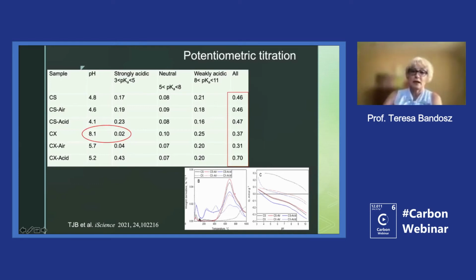We also did the thermal analysis. So here are DTG curves, so we could see what was the weight loss and what was really removed on the surface. And here is what we got. Okay, so what was interesting with carboxane is that it was the only one basic carbon. Completely different from others. It really didn't have the strongly acidic groups on the surface. And so that basicity was quite puzzling.